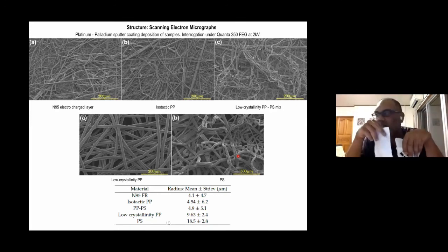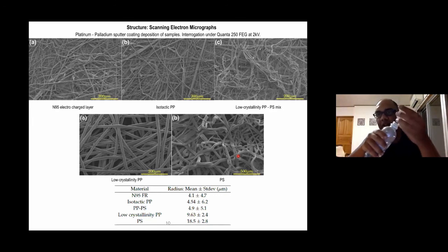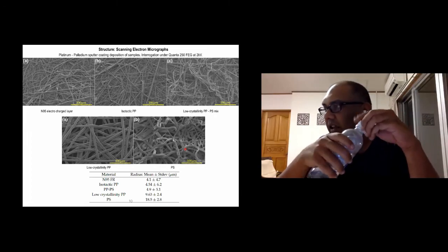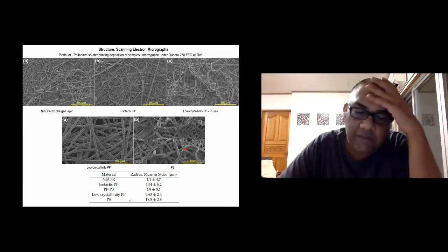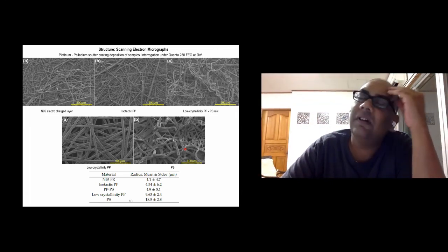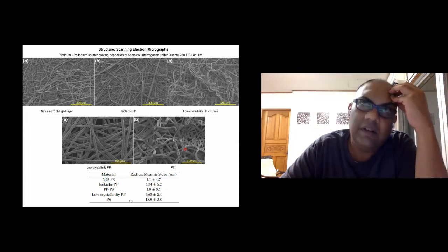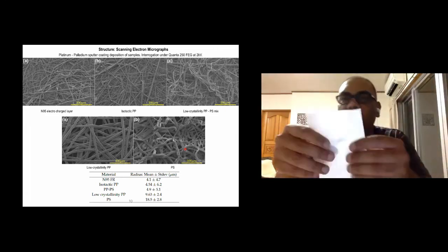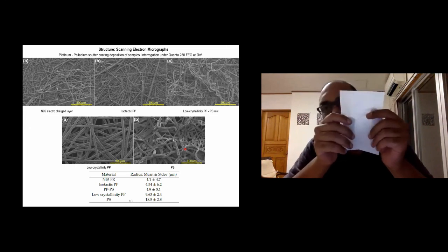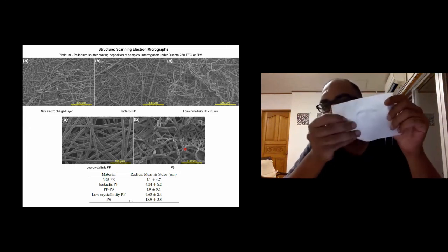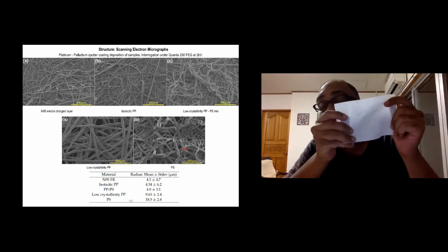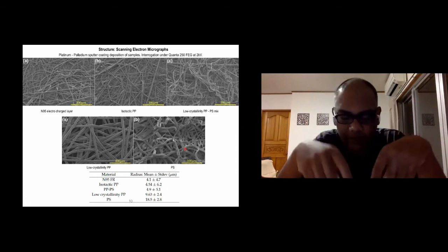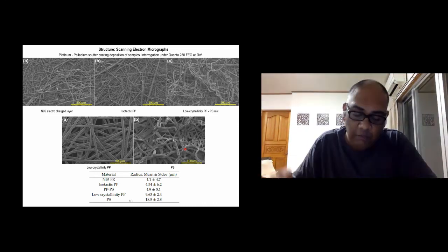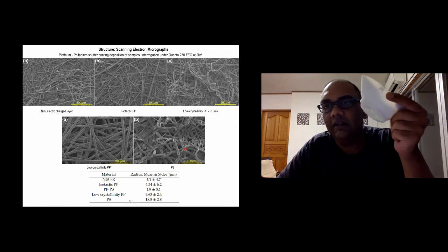The fabric is actually quite cheap. As I said, I was using polypropylene from these bottle caps. The ones we sourced commercially from Sigma Aldrich were of the order of $50 for 5 kilograms, and this one is about 12 grams. So you can make lots of fabrics with 1 kilogram, which would be about $10. So it's very cheap that way. The most expensive part is actually this, but you can reuse it.